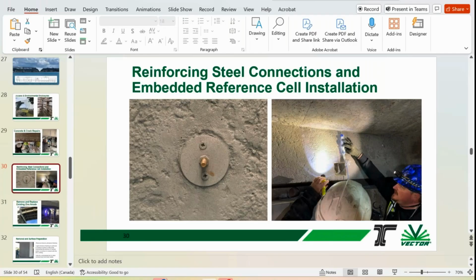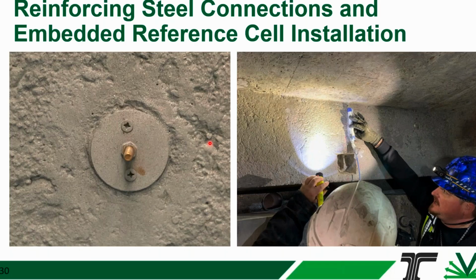Okay, so on the left-hand photograph here, you see one of the electrical connections that's installed on the surface of the concrete, but this brass pin actually goes back into the concrete to connect to the reinforcing steel. This allows you to electrically connect to the reinforcing steel from the surface of the concrete. Those are put in on a spaced basis as required in the specification. And the other thing that you need to have installed in the concrete are sensors. We call them reference electrodes or reference cells. They are embedded inside the concrete and they allow you to measure the potential or the voltage of the reinforcing steel while the system is running, and that's a way that you can verify the performance.